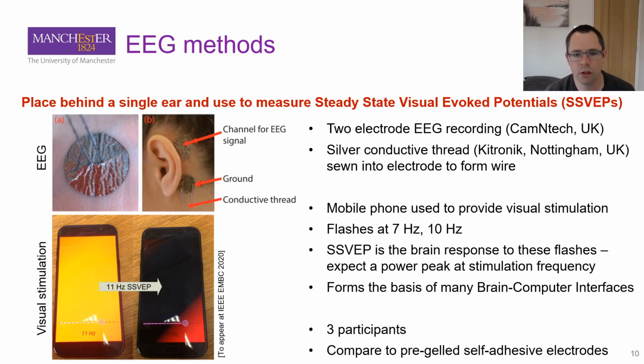To verify the functional performance of the electrodes, we recruited volunteers and put 2 electrodes behind a single ear. To give us a known signal to record, we showed a flashing light to our users. And what this produces in your brain is a response known as a steady state visual evoked potential. So if you flash a light at 10 Hertz, say, your EEG will have a peak in the frequency domain, in the power spectrum, at 10 Hertz. And this is the basis of many brain-computer interfaces. You can imagine if you've got a screen with lights in different corners flashing at different frequencies, you can look at the EEG to see what the dominant power frequency is, and from that determine which of the different squares the person is looking at.